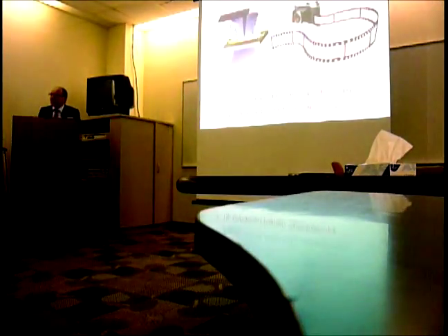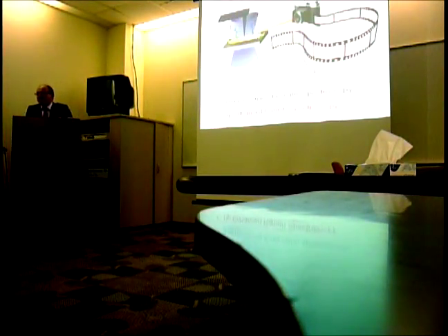And its chemical information, for example, is shown here when we do Fischer-Tropsch. And here you see what is happening when the catalyst is exposed to CO and hydrogen at 350 degrees C. You see the gradual formation or reduction of the iron towards its carbidic form in this material. So this is a kind of showcase of what nowadays is on the frontier of X-ray microscopy for catalysis research.